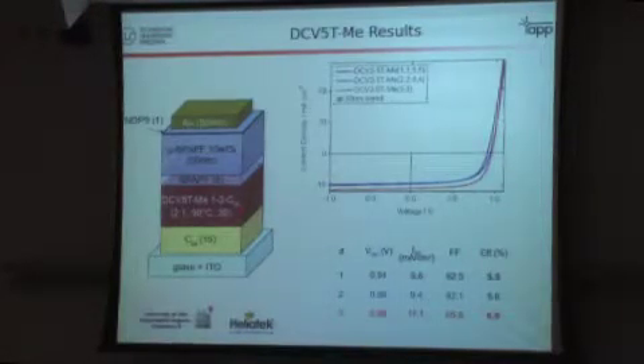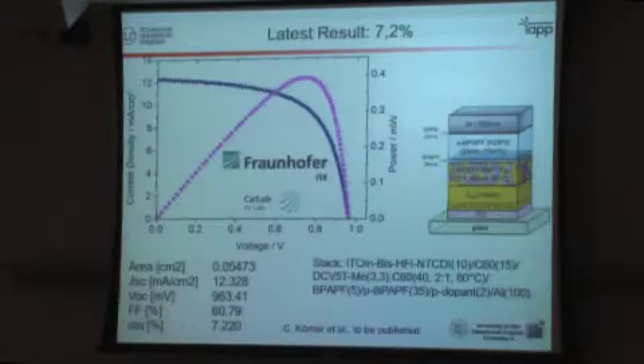Keep in mind that when you look at this solar cell of 6.9%, it has an active layer of only 30 nanometers. That is because we have insufficient mobility. If we had a mobility 1 or 2 orders of magnitude higher, we could do 100 nanometers and would be well above 10%. But so far we haven't managed that yet.